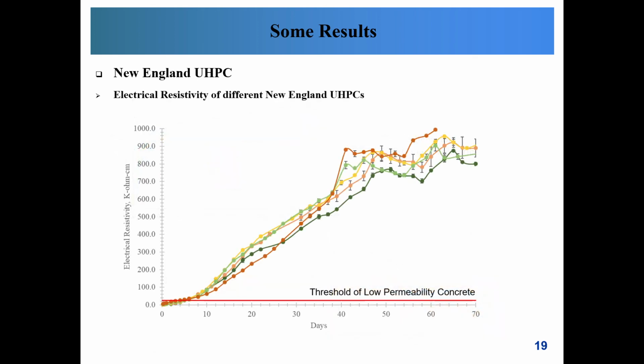Last but not least, you see here preliminary results of the electrical surface resistivity over the age of the UHPC. The threshold of the definition of low permeability concrete has been plotted here in red. So after 4 days, UHPC surpasses already the threshold of 27 kiloohm centimeters and continues increasing the resistivity until reaching a measurement of 1000, which reaches the detection limitation of the equipment. This means that the pore structure indeed extremely densifies with aging of the concrete, and this is a key property for long-lasting durability of the material. So this is good.